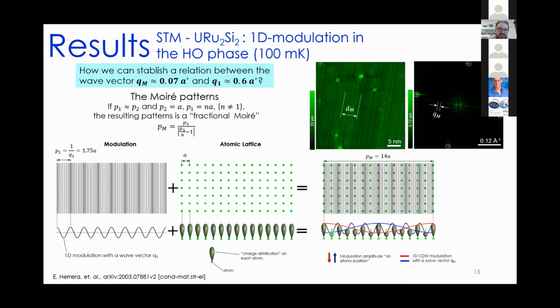Here we represent how the modulation changes the size of the lobes, as you can see here. And the size of the lobes leads to a pattern that can be fitted using two cosines, as you can see here with the red line and the blue line. And the cosines have the same periodicity, but they are shifted by pi. And this particular situation is a characteristic feature of the fractional moiré pattern.